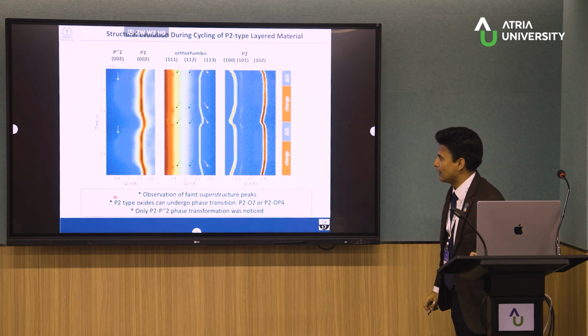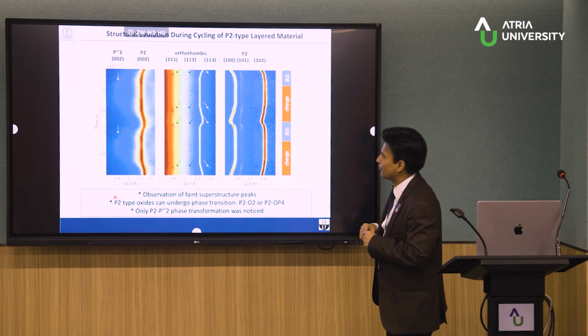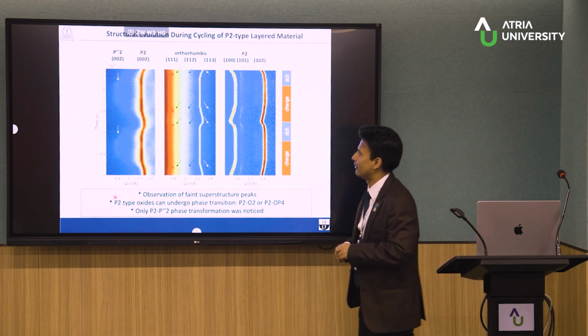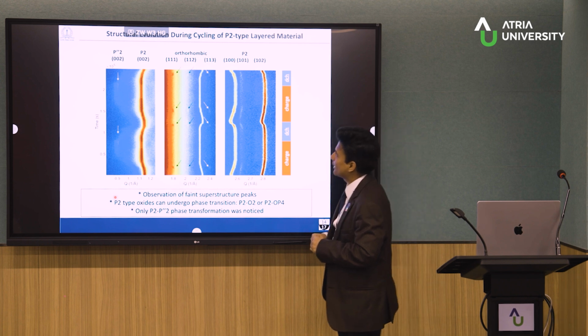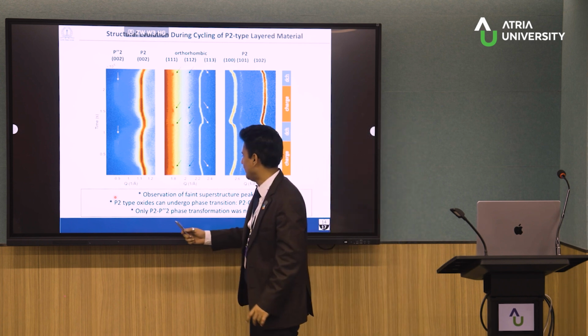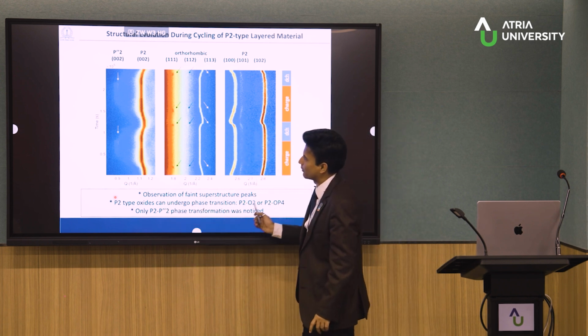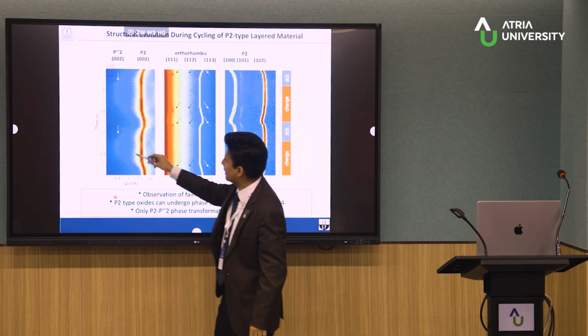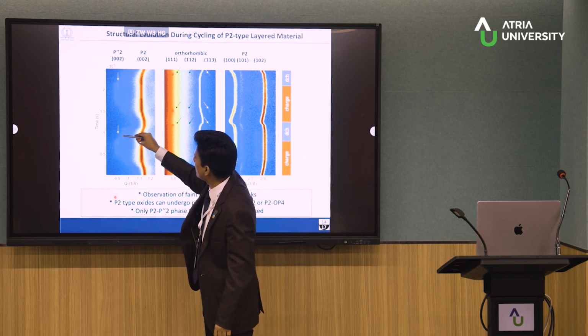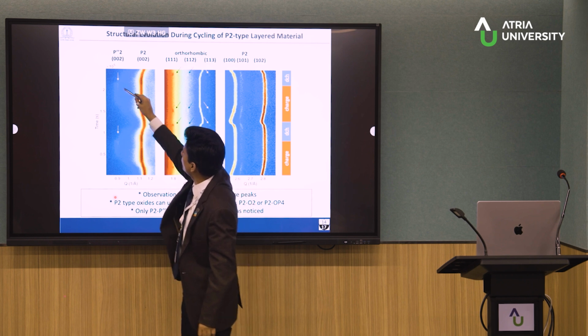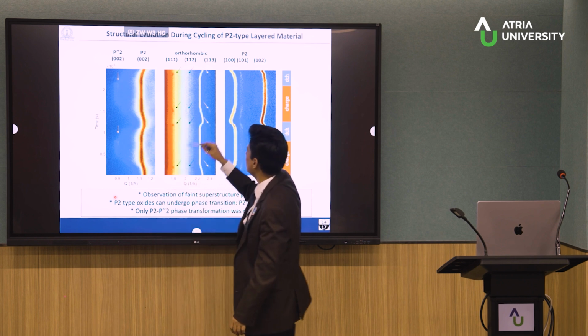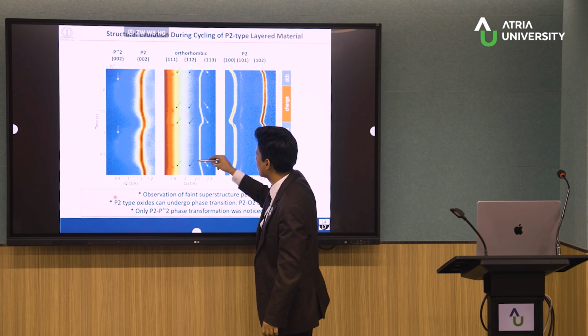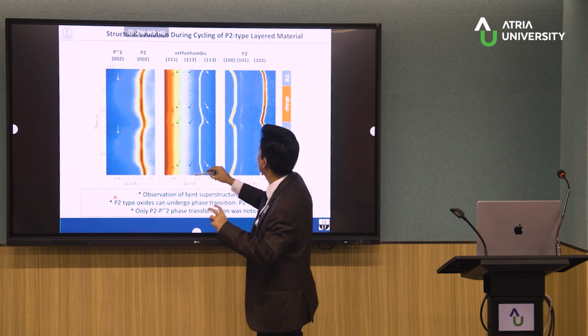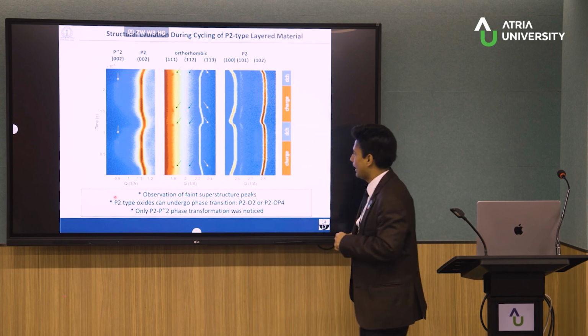Now in Austria, we did some in situ X-ray diffraction for this material, and in the in situ X-ray diffraction you can also see an observation of faint superstructure peaks. It may not be clear, but here you see during charge, at a particular point, some new peaks appearing. These are the superstructure peaks, and at these points we also see some extra, very feeble, small intensity peaks. These are the superstructure peaks.